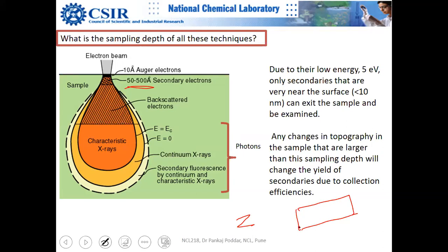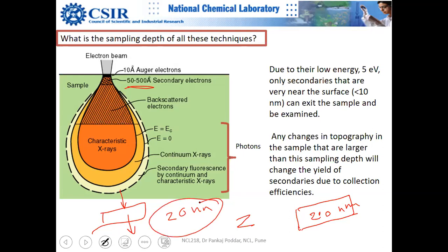For polymers you can take a sample as thick as 200 nanometers, while for gold you cannot go more than 20 nanometers for transmitted electrons. There is a tenfold difference. The reason is that atoms with more electrons have stronger Coulombic interaction and scatter more strongly.